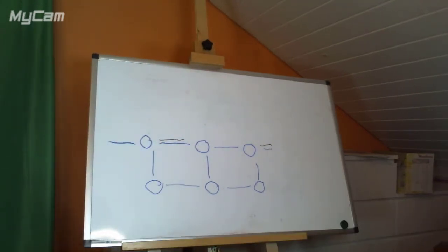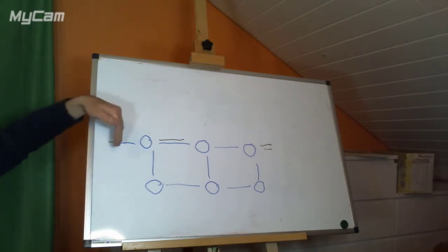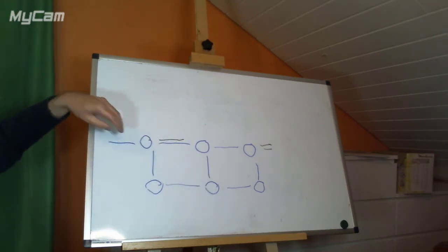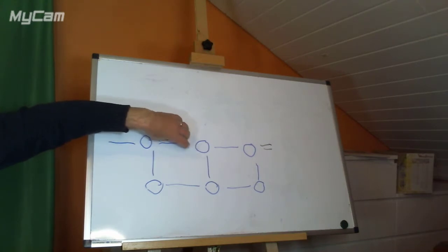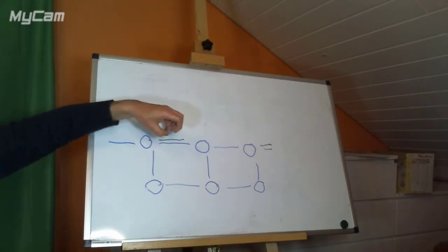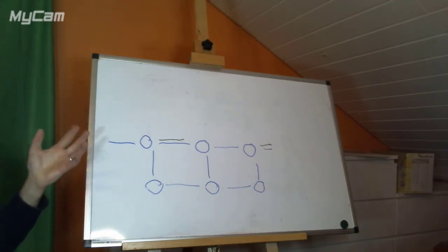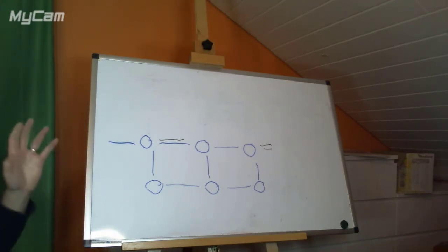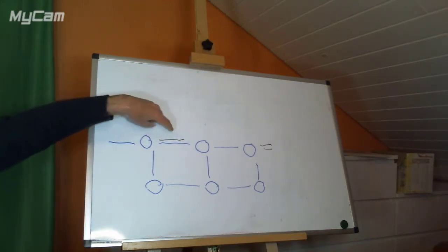This is what we really see. If we look at the crystal structure of silicon in a silicon wafer, we can measure the bulk crystal structure, and it has a certain distance between the atoms. And if we measure at the surface, we see more distance between the atoms, and they are actually bunching up into pairs and stitching together. So they've got an extra bond, they're closer together, and that uses up the extra bonding density and changes the surface, makes it less reactive than it would otherwise be.